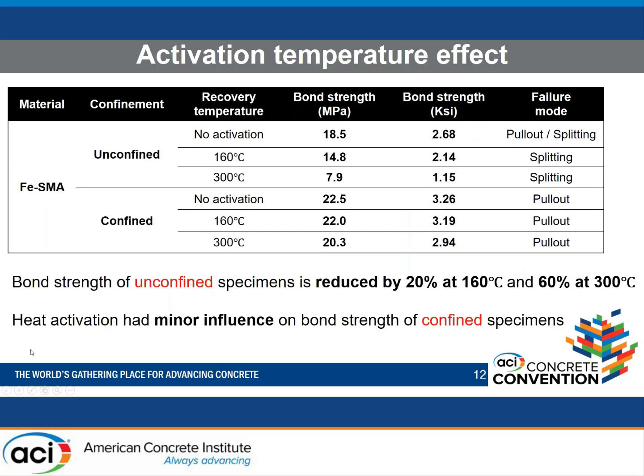Just to make it clearer for you, I'm summarizing the results in a table here. So SMA bars with unconfined, we have huge reduction in bond strength from 18.5 megapascal to 7.9 megapascal. While if you look at the confined cases, you will see a very minor influence of the heat activation as the bond just reduced from 22.5 to 20.3 megapascal. And these are the numbers in KSI, if you prefer the KSI unit.